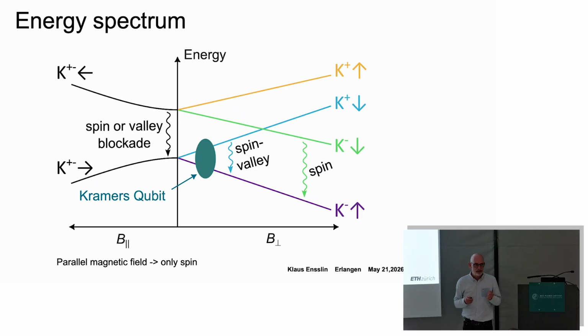So it's not given just by graphene, it's given by the band structure and by your electric fields in your system. So you see this valley-Zeeman effect. And of course, you also have the standard spin-Zeeman effect. And you see that's the reason why, for example, the lower doublet splits more, because it splits by valley g factor plus spin g factor. And the upper one splits by valley g factor minus spin g factor. In this particular case, the valley g factor is around 20. The spin g factor is 2. So it's 20 plus 2 and 20 minus 2.